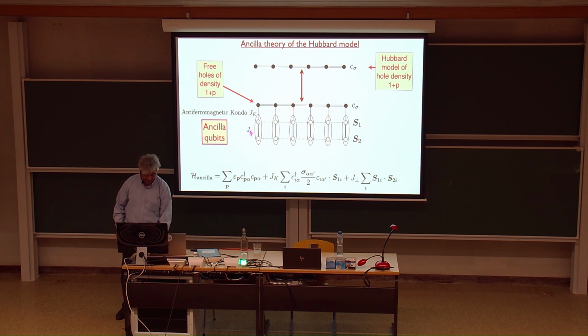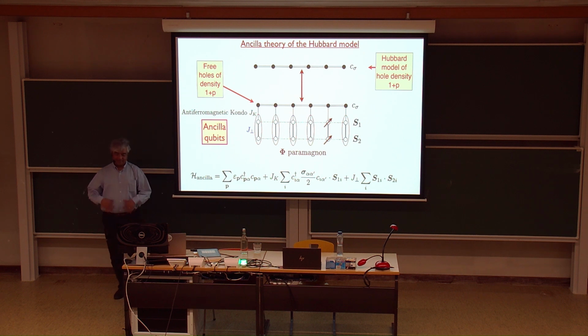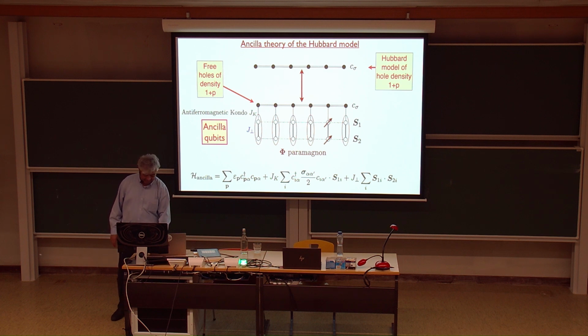But what are the excitations of these extra layers, or ancillary layers? There's an excitation which is this triplet, and this can move around, and that's my paramagnon. So I claim that I can rewrite the Hubbard model as this 3-layer model where the bottom 2 layers have a spin-1 paramagnon, and the top layer is coupled to the physical layer by antiferromagnetic exchange coupling J Kondo.